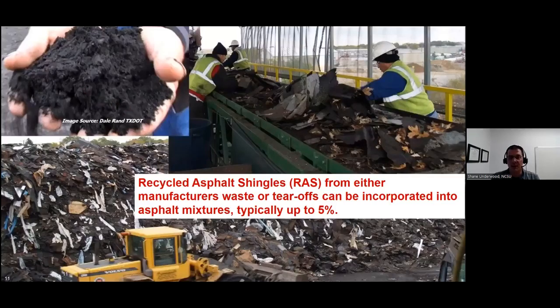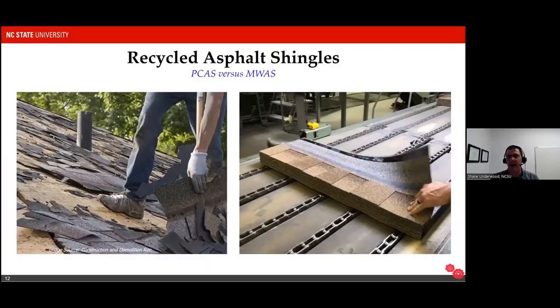But usually once the materials are sorted, they're ground into a fine powder essentially, and then those get blown back into the asphalt mix at the centralized plant. Another image here just to emphasize that there are two streams of asphalt shingles. The so-called post-consumer asphalt shingle is taken directly from people's roofs. This material may have been sitting in service for 10, 15, 20 years. So it's going to be stiff. It's also going to be much more varying in terms of composition and behavior.